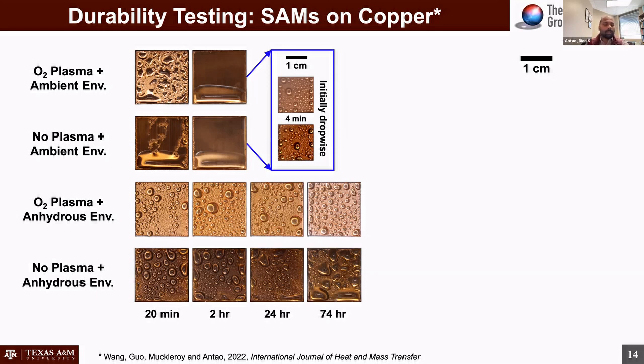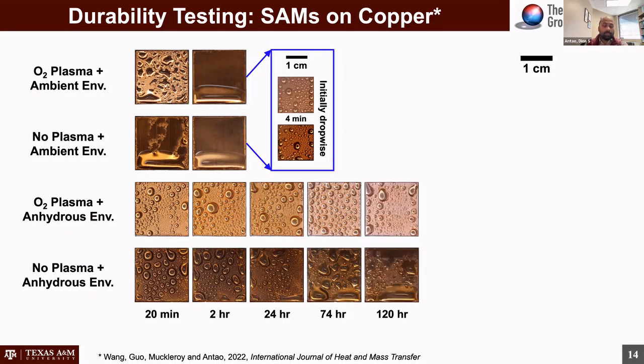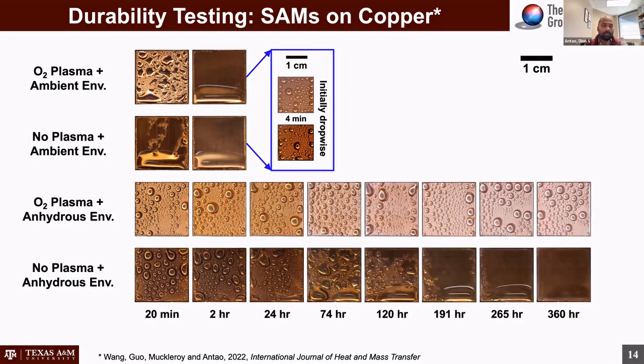Okay. And the oxygen plasma in the anhydrous environment actually performed fairly well right up to when we stopped the experiment at about 360 hours. And so we clearly see the benefits of the right surface chemistry, as well as minimizing the amount of water present in the coating environment.